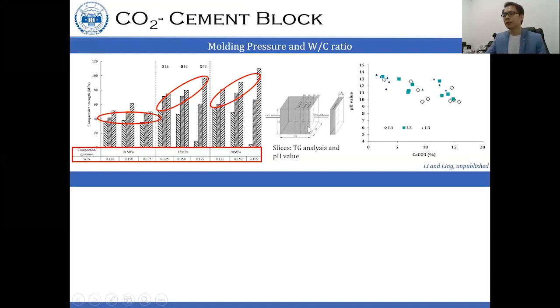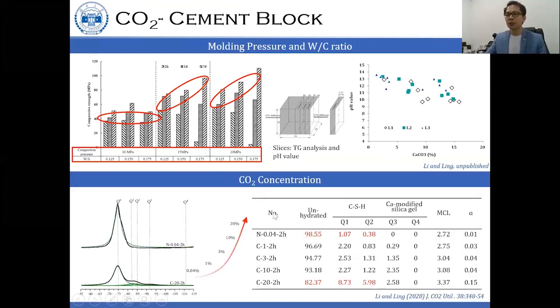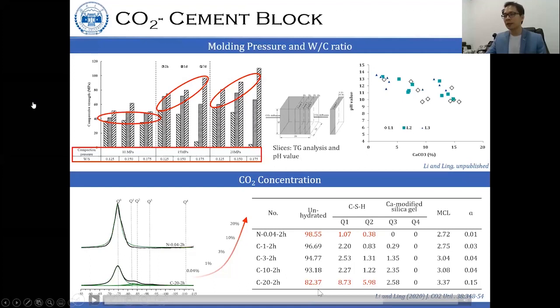We also test the different layers for the TG to calculate the calcite content and to measure the pH value. And we found there is a good correlation. And for the CO2 concentration, as we increase the CO2 concentration, actually based on the result, we found that it could help for the cement hydration and also for the CO2 reactions.